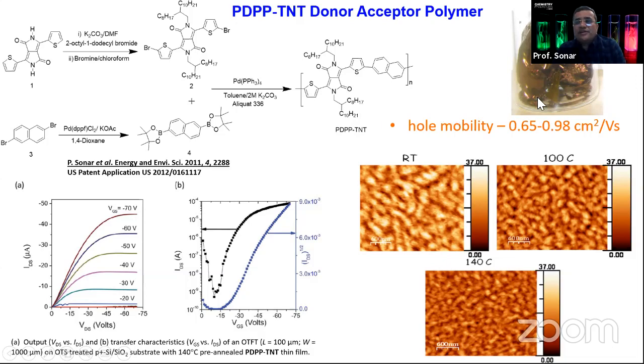Now looking at this polymer, here we put in an electron donating group called naphthalene. Acenes are very well known, as most organic electronic people know that pentacene is a very classical semiconductor people are using. This is the small brother of pentacene, which we call naphthalene. There is another brother, or sibling, called anthracene, and these longer acenes have 6-membered benzene rings that can fuse together. So this is more donor. So donor, thiophene donor, again this donor, and this is only one acceptor. We have 4 donors, so we have more donor as a majority.